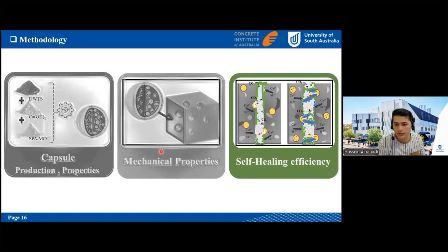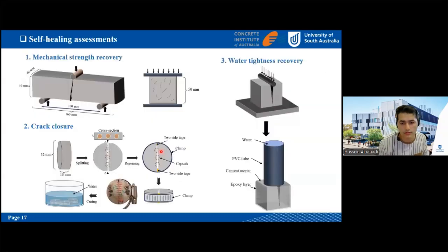So in terms of the self-healing efficiency, we had three to four types of tests. We tested the mechanical strengths to see how it recovers the strength. So we crack the samples, with this test we generate some cracks in both cubic and beam samples, and then put them for healing in different times to see how much strength will be recovered after the healing times. Another test we've done is to see what's the maximum crack that can be closed by the capsule. So we generate some samples and create some artificial cracks with different widths up to 1 millimeter, and see how much of this crack can be healed.